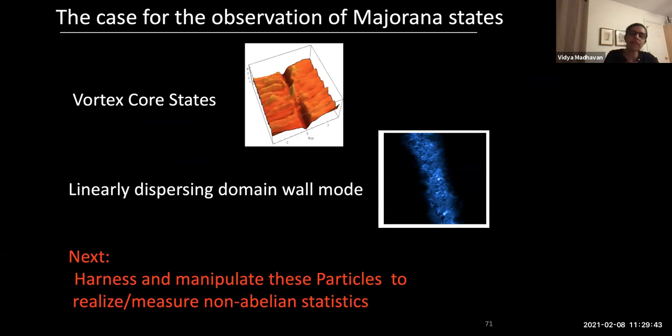And then the first experiments that we did with the vortex cores were really puzzling, because like the other group had found, we found that just a small portion of the vortices showed these zero bias states. In fact, most of them didn't, because we were applying a 5 Tesla field. But as we worked more and more with this material,